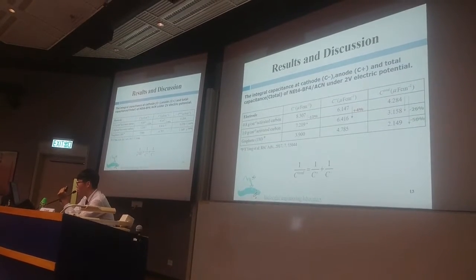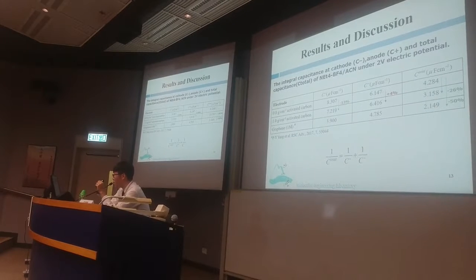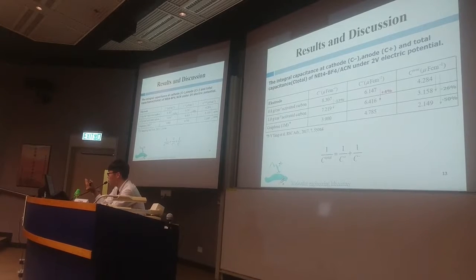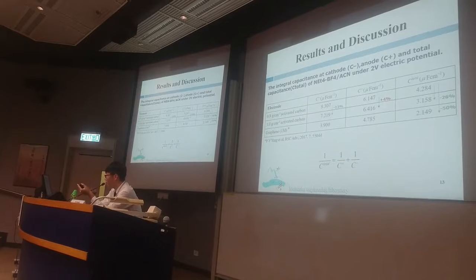And finally, we compare the AC electrode and the graphene electrodes. Because the AC electrode has higher specific surface area, the AC electrode has more capacitance than the graphene electrodes.